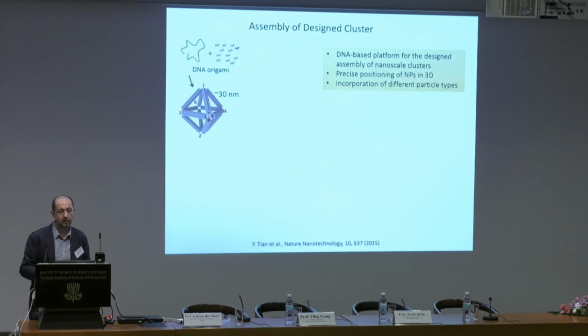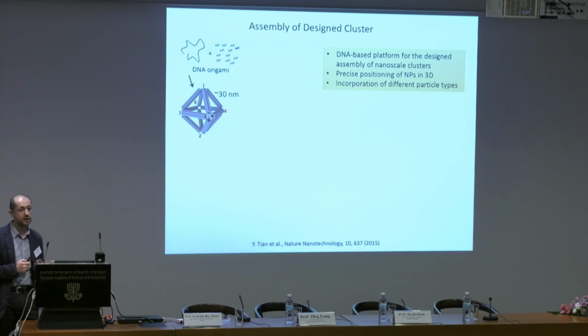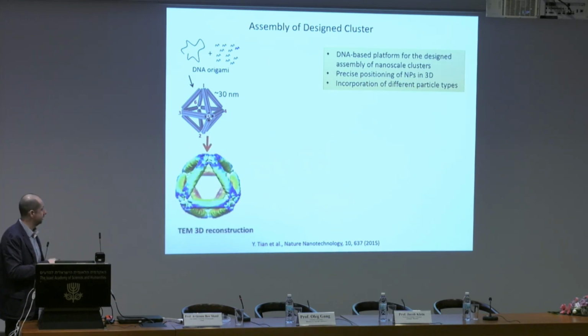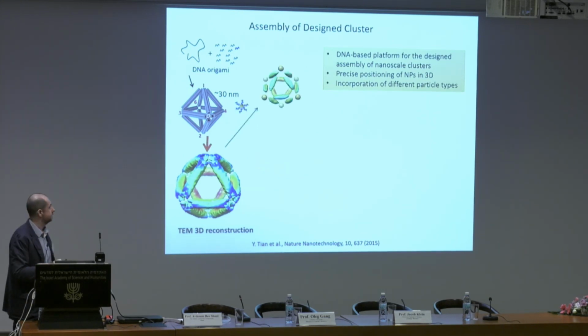Now, imagine that we have this idea in mind that we can build 3-dimensional, quite complicated linkers, and this linker has a very particular geometry which we can predefine. So this is what we are doing here. This is an octahedron. It has dimension approximately 30 nanometers per side. And so those 1, 2, 3, 4, 5, 6, those are vertices which can be prescribed to have different addressability through the incorporation of single-stranded DNA. First of all, we can confirm, using cryo-TEM, that we can create this type of object. And second, we can use those vertices essentially as an underlying scaffold to position particles in 3D.